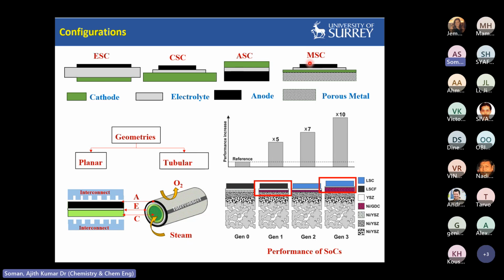And finally the metal supported, where you have an additional mechanical support as a porous metallic layer or metallic substrate at the bottom. You can develop all the corresponding layers on the top. So you can have the cathode on the metal layer, and you can have the dense electrolyte and the anode on the top. If you look at the different generations, the metal supported cells are very promising in terms of performance, durability and mechanical stability. Everything is fantastic. So if you look at this generation, the metal support with the various layers, especially with the electron blocking layer and the cathode with different porosity, you can see the same nickel YSZ, nickel GDC in different layer thicknesses will enhance the performance.